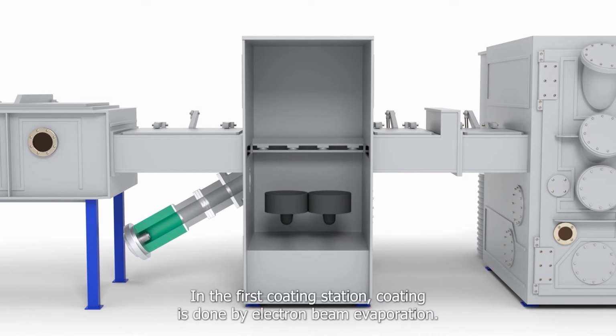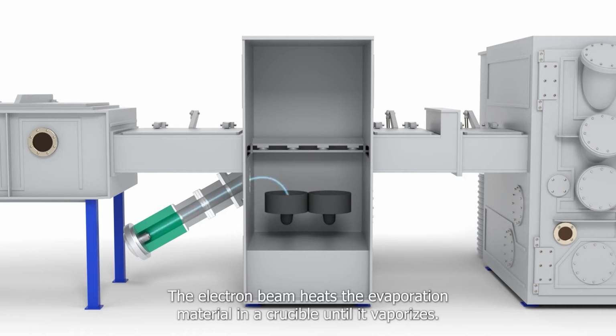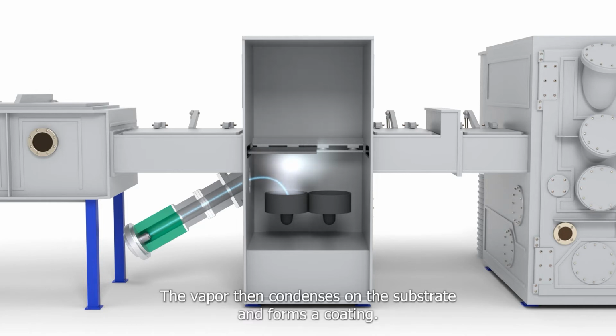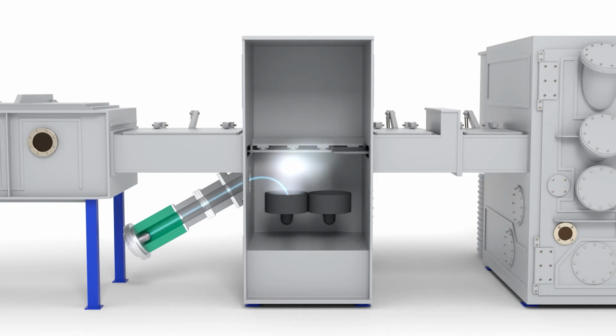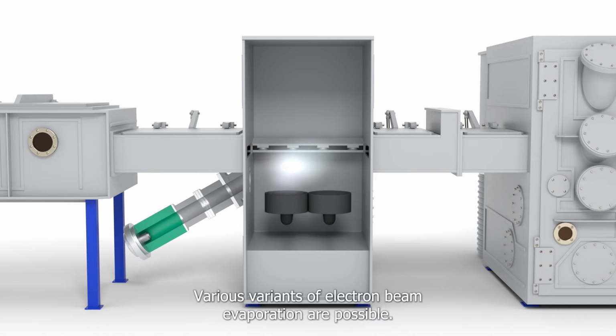In the first coating station, coating is done by electron beam evaporation. The electron beam heats the evaporation material in a crucible until it vaporizes. The vapor then condenses on the substrate and forms a coating. Various variants of electron beam evaporation are possible.